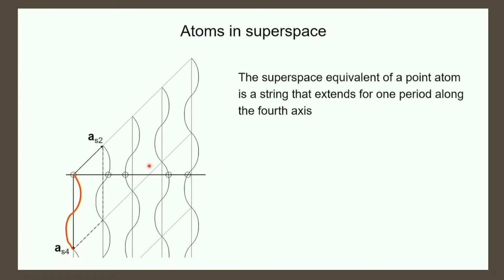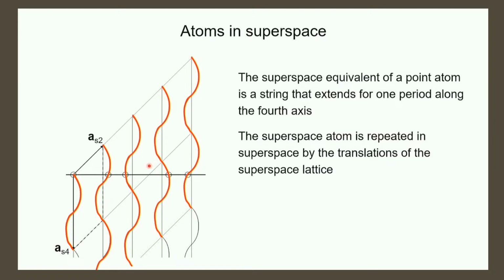So to summarize that, the superspace equivalent of a point atom, as we often use, is not a point anymore, it's a string, here given in red, of 1 unit cell long and on the average perpendicular to physical space, meaning on the average along the fourth axis. And then we apply again all these translations, so it's easy.